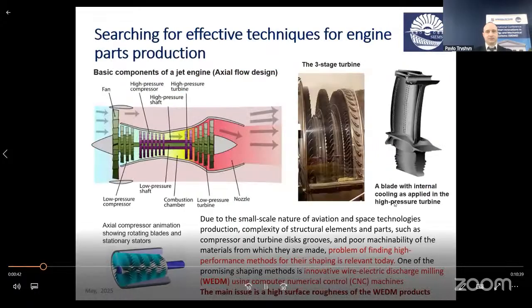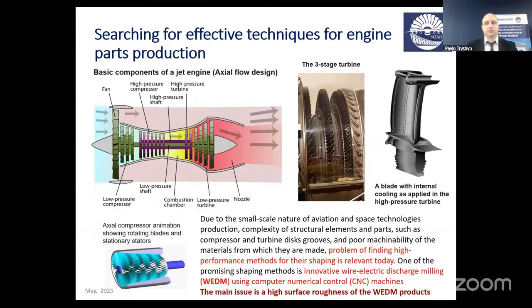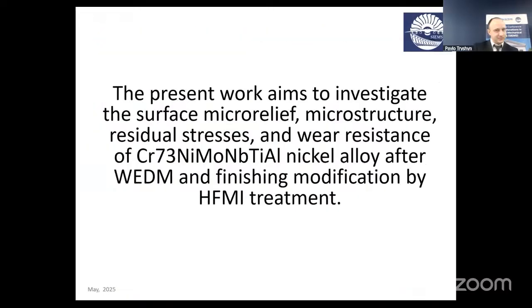Searching for effective methods for engine parts production is a very timely task. It is well known that engine contains numerous parts of complex shape, like the blade shown here on the right, and thus the problem of finding the high-performance methods for shaping these parts is relevant. One of the promising methods is innovative wire electric discharge milling using computer numerical control machines. However, the main issue with this method is high surface roughness and deteriorated properties of the WEDM-produced parts. Therefore, the present work aims to investigate the surface micro-relief, microstructure, residual stresses, and wear resistance of nickel alloy after WEDM and finishing modification by high-frequency mechanical impact treatment.